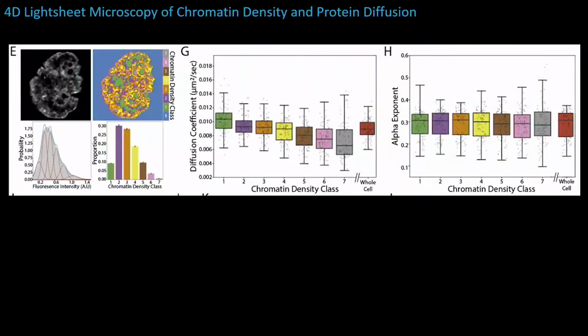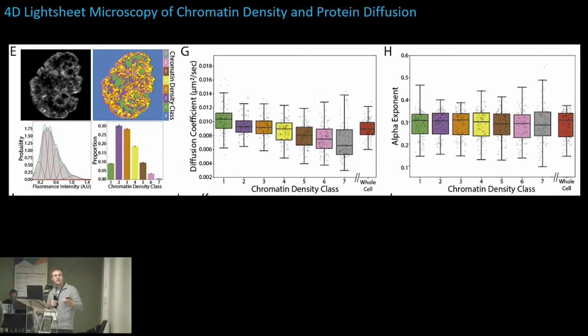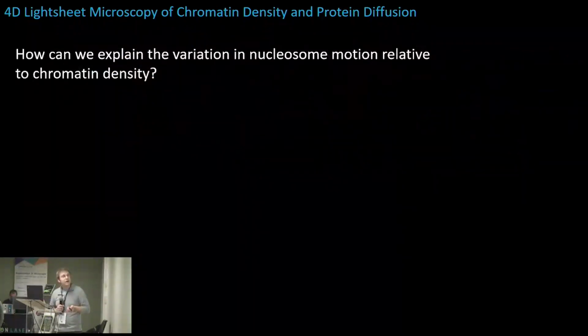So if we plot the apparent diffusion coefficient and the alpha exponent for nucleosomes in different chromatin density classes, we can see right away that there's a clear trend where nucleosomes in these denser chromatin regions are, we'll say, not necessarily more confined, so they don't display more anomalous diffusion. It's all confined diffusion, but they move slower and they move less. They appear to be less mobile, less diffusive than nucleosomes in these low density chromatin regions.